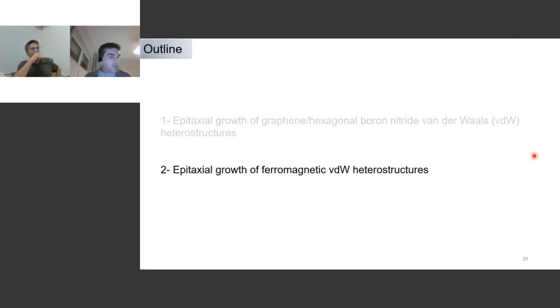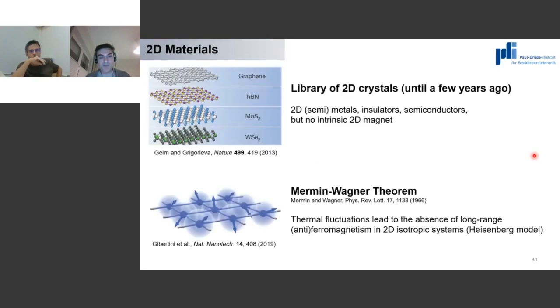Now let me go a bit quicker than planned to the ferromagnetic heterostructures. I just want to say that if you look until a few years ago at this library of 2D crystals, as I showed you in the beginning, you would see graphene and the 2D semiconductors, boron nitride, but there is essentially no 2D magnet. And this was not seen as a big surprise because, well, what is expected according to the Mermin-Wagner theorem is that thermal fluctuations would lead to the absence of ferromagnetism or long-range magnetic order in 2D systems. So basically the Heisenberg model here, that you don't have spin alignment and so on.